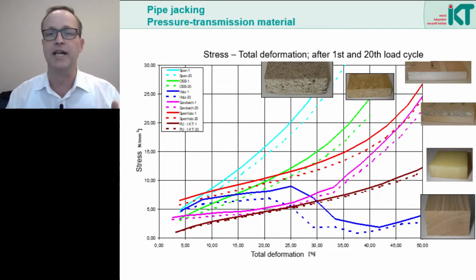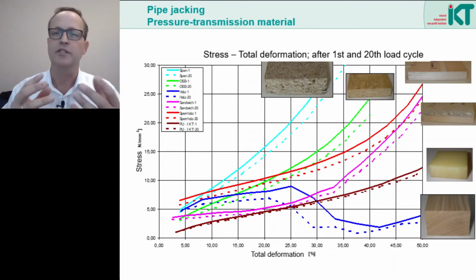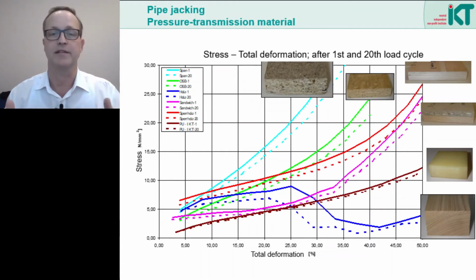Above we see the results for a chipboard. This behaves largely linear elastic with small plastic portions under repeated deformation. The curves for the 2 other wood-based materials, an OSB board in green and a plywood board in red, have a similar but a bit flatter shape. For the other materials, however, the curves look completely different. The pink curve stands for a material combination including plastic, wood and steel and has a bend at about 33%.